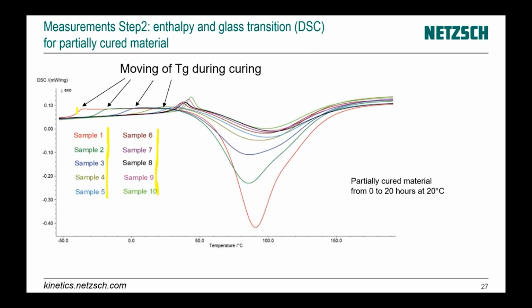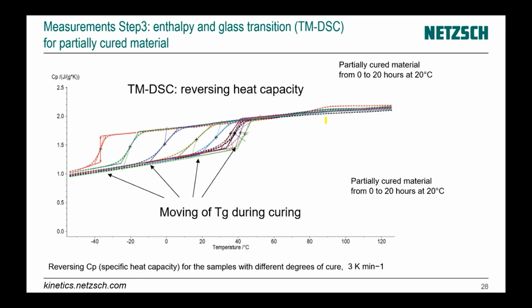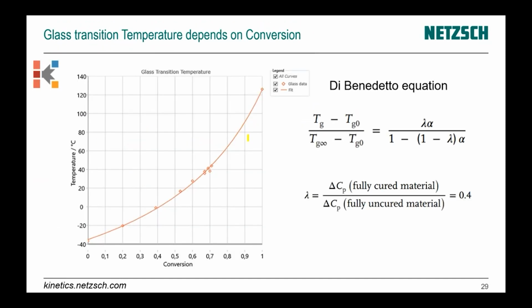But here we are able to find the glass transition only for 4 of these samples, because for other samples, the glass transition is somewhere during the curing. Now we use temperature modulated DSC in order to find the glass transition for all 10 samples which are partially cured, and after that we have the dependence of the glass transition temperature on degree of conversion. And here are our measured glass transition temperatures for each partially cured material. Then here again, totally cured and totally uncured.